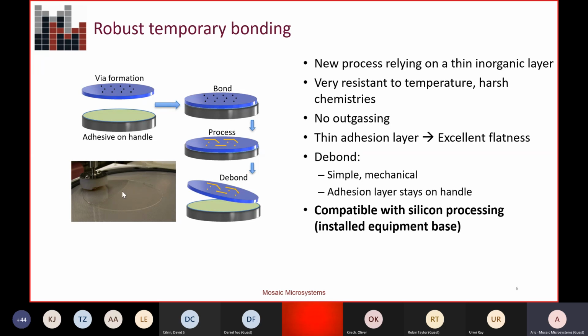So the cartoon on the left is showing the debond process. It's a room temperature debond. There's no laser separation, no chemicals, no high temperature. You essentially initiate the debond near the perimeter, and then it's a mechanical peel to remove the wafer. Generally, we'll put the thin device wafer down on dicing tape and peel away the thicker handle wafer. This cartoon is showing a glass handle wafer just so that you can see the debond front through the glass. But once you initiate that debond, it's really a well-controlled mechanical peel to remove the handle wafer.